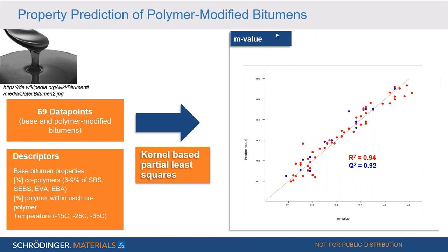In a similar fashion, we can also look at the M value. The M value is basically a measure of the rate at which the stress is relieved. So if we have a low M value, this means a lower relaxation. So it's also important to know this parameter in order to assess the performance of the polymer modified bitumens. And we see also here for the prediction of the M value using machine learning, we get quite good agreement between given or experimental and predicted M value. So we have R square values of over 0.9 for both training and test set.